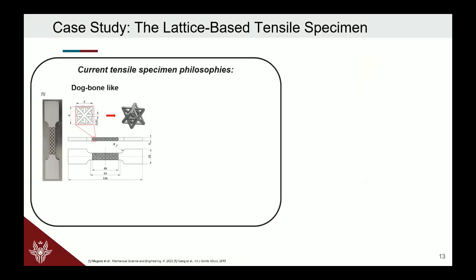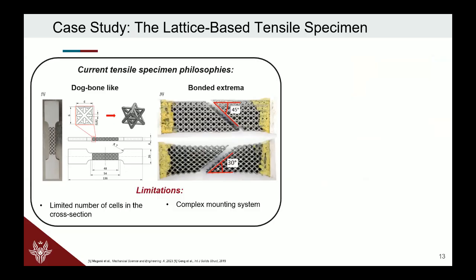Another important point is that, dealing with these cellular structures, in particular with fatigue loading but also with static loading, what is missing is standardization for the specimen that we need to use. So what we tried to do as a second step was to create a standardized sample which allowed failures in the middle of the specimen, always repeatable for different lattice geometries.